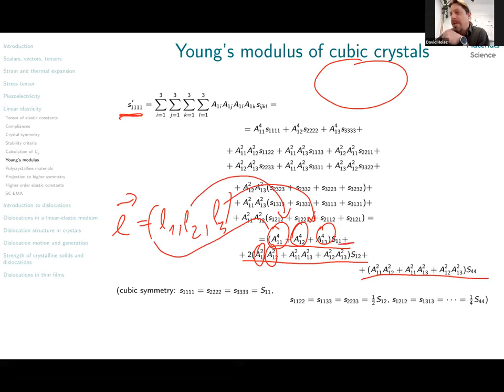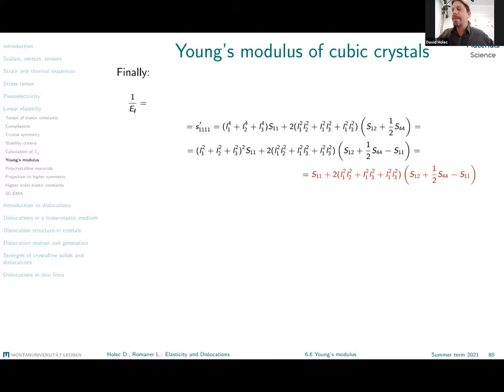We have already used in here the fact that we have cubic material. So we have simplified those values that we know are identical in the cubic material. And we have also used the Voigt's notation here. Don't forget that while for the elastic constants the Voigt's notation is straightforward, how to go from 4 to 2 indices, for the compliance matrix and compliance tensor the relationship is more complicated. We have these additional factors, 1/2 and 1/4. When you put all of this together, you finally come to the expression for the cubic materials.